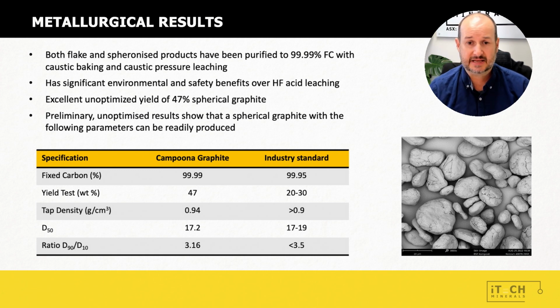Now, our tap density, that's the amount of material that you can fit into any given space. So the more of this spherical graphite anode material that you can fit into the anode of a lithium-ion battery, the higher the performance of that battery. So if you get it over 0.9, you're well above the industry standard, and ours came in at 0.94.